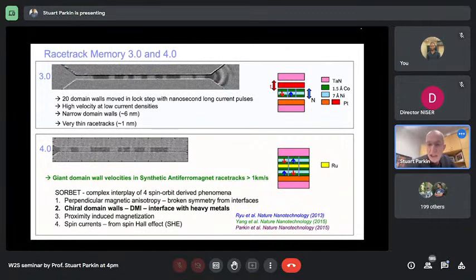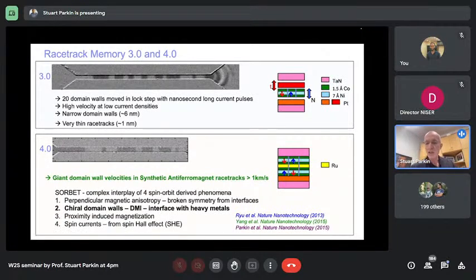We eliminate all dipole fields. And we also discovered in this paper we published in 2015 that the domain walls now move up to 10 times faster than in a single magnetic layer. We discovered a totally new type of spin orbit torque, which is derived from the strength of the antiferromagnetic coupling field through ruthenium. That magnetic field gives rise to a huge torque that's much more effective than the torques derived from the spin Hall effect. So this is very interesting. And now we can move these domain walls in these synthetic antiferromagnetic racetracks at speeds of more than 1 kilometer per second.